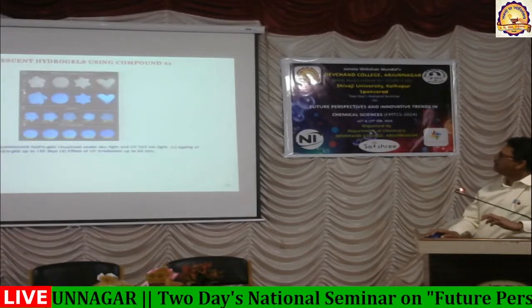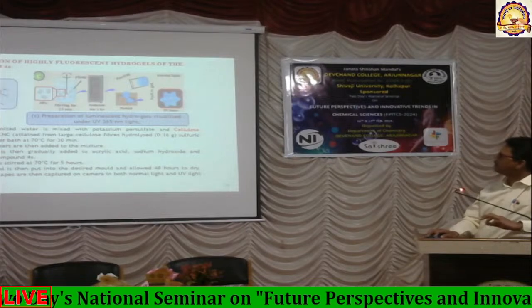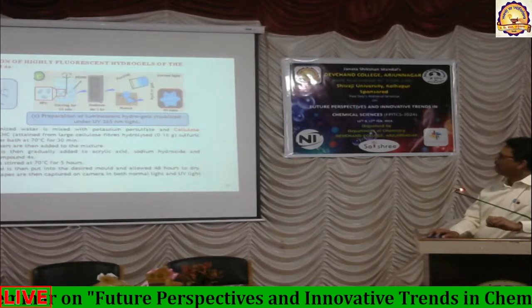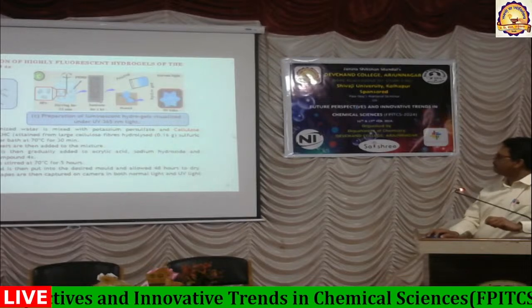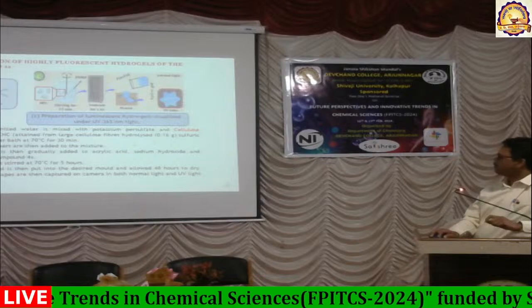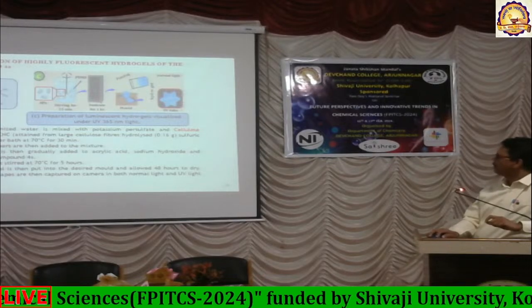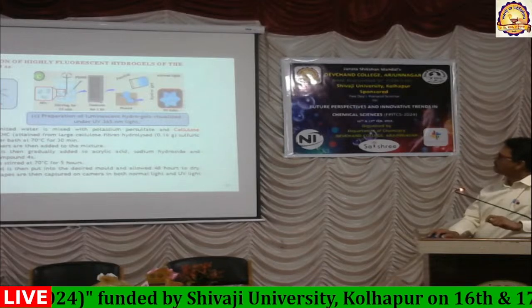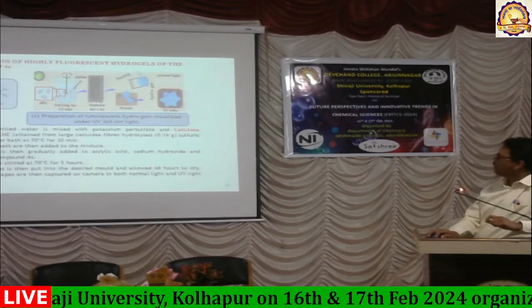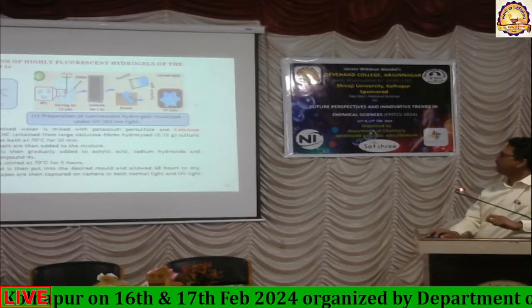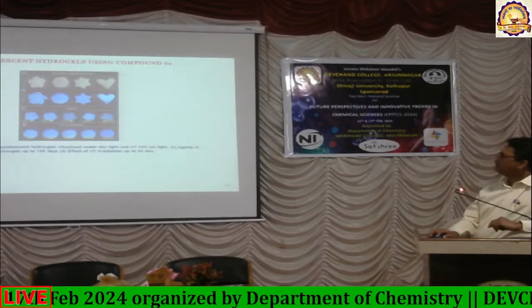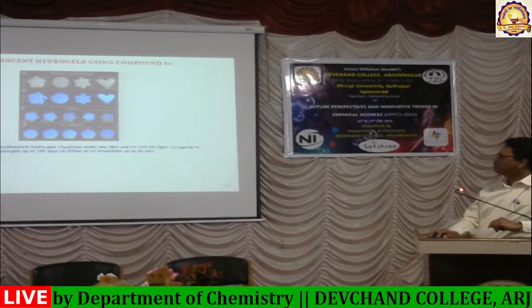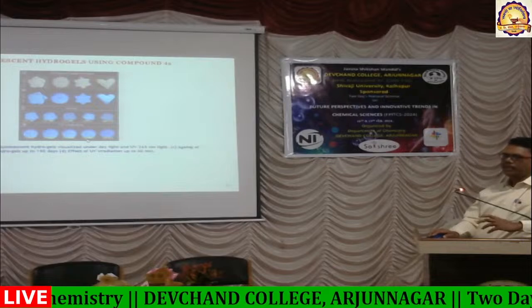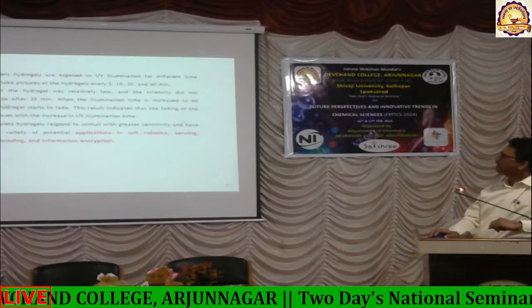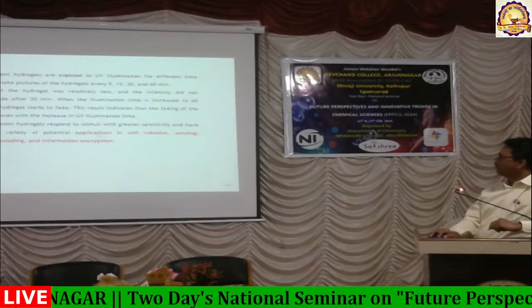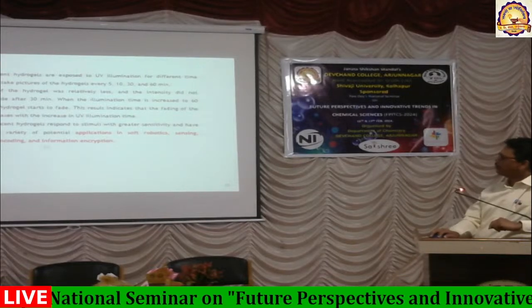So these are the fluorescent hydrogels. We can even make molds of this using the same kind of compound, mixing it with cellulose nitrate and then sulfuric acid, and heating on a water bath. We can get the slurry of this with the synthesized fluorescent compound, so that a mold can be prepared, and we can have a mold of our own choice. Different kinds of molds you can synthesize, which can glow upon irradiation in the UV light. So this kind of molding, the hydrogels, can have various applications in soft robotics, sensing, information encoding, and information encryption.